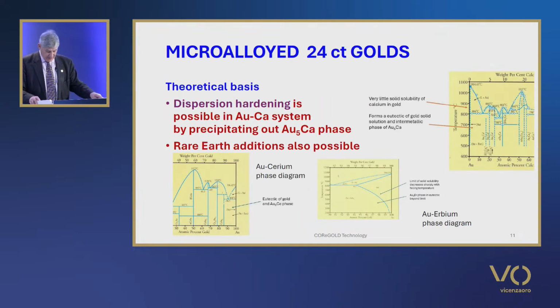If we look at another light metal, calcium, a gold 0.5 weight percent calcium alloy is only 2.41 atomic percent calcium, which is quite small, only 1 atom in 40, and therefore would not be expected to provide much solid solution strengthening. However, reference to the phase diagram, which is over here on the right,